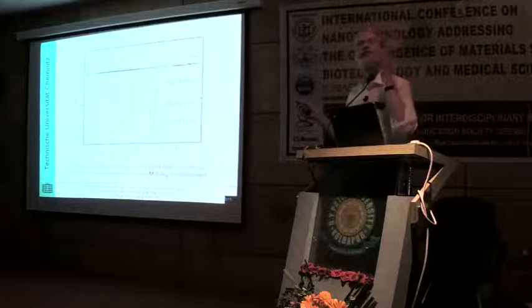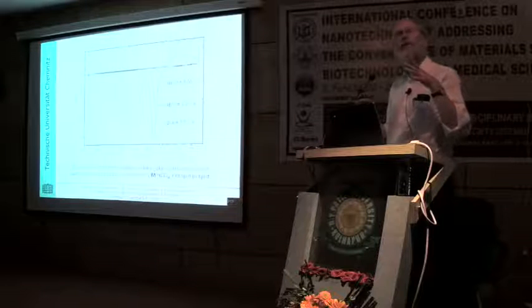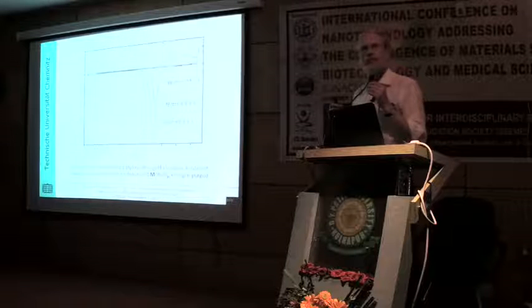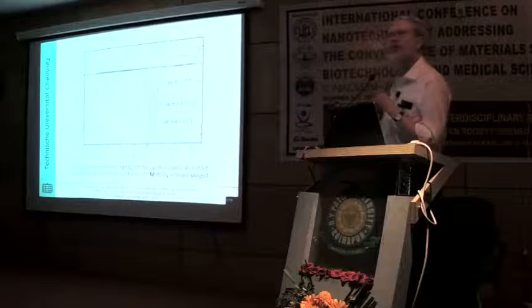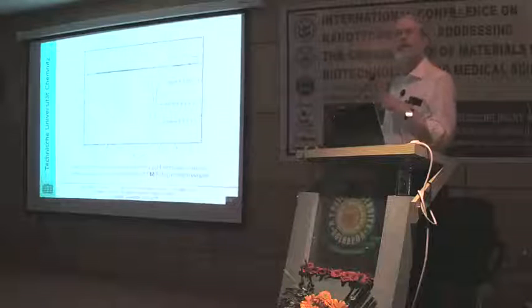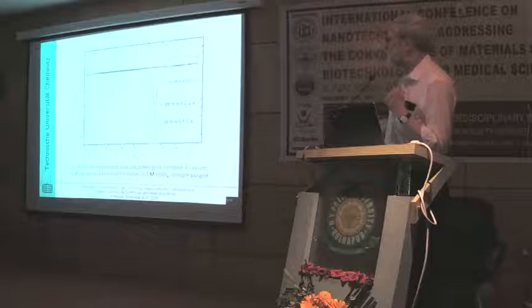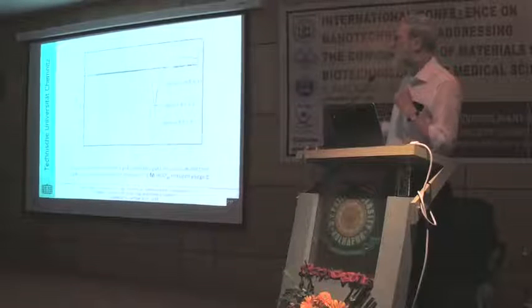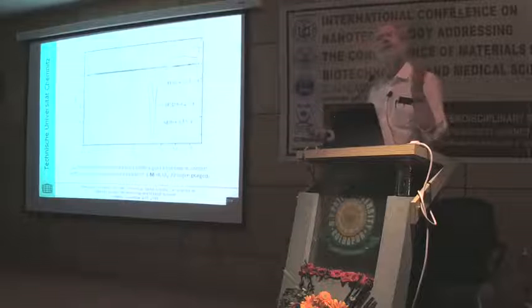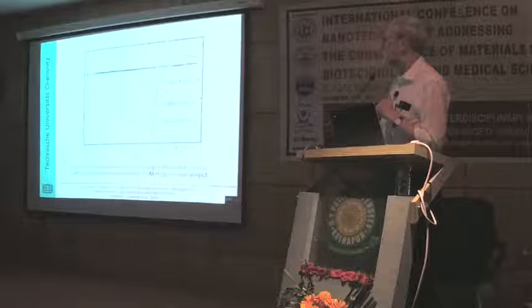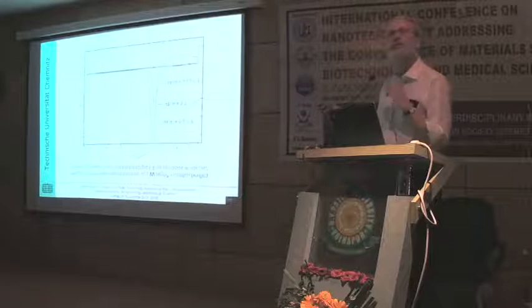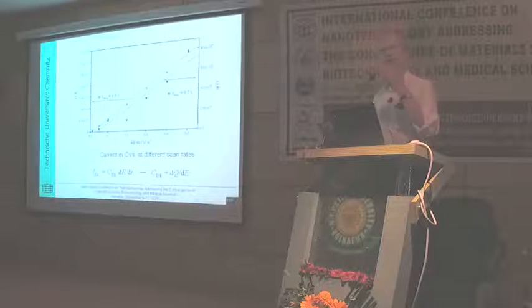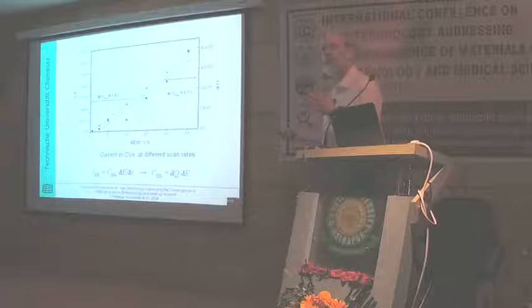What is going on in this range? In this range, we are oxidizing water and gold, and we form a layer of gold hydroxide on the gold surface. And this gold hydroxide is slowly turned into gold oxide, and finally, when we go on, we will make oxygen by oxidizing water. When we go back, we reduce this oxide or gold hydroxide layer, and once again, in this range, we are in the region of pure double layer charging. So both this capacitive current as well as this current, which is due to some redox process, look like capacitive. But since we know this much larger current is due to a redox process, this behavior, this linear relationship, has been called by Brian Conway and co-workers pseudo-capacitive.